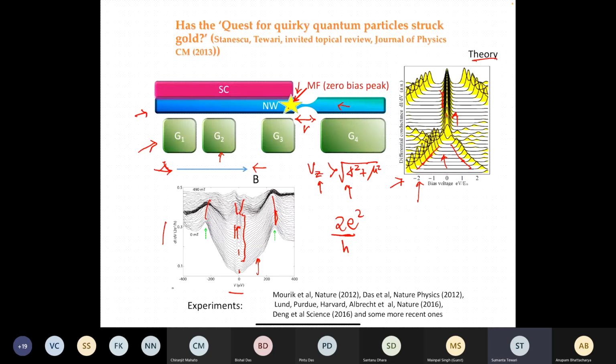If it's any other zero energy state due to, let's say, impurity scattering, an impurity state, or some other Andreev state, the peak height can be greater than 2e²/h all the way up to 4e²/h. Now, forget about 2e²/h, 4e²/h. The peak height that they found here is like 0.1 e²/h. So it's orders of magnitude smaller. All right. So that's what I said, a fraction, 0.1 times 2e²/h.